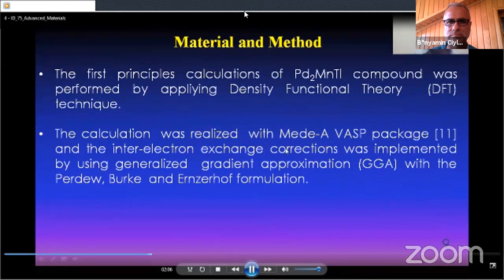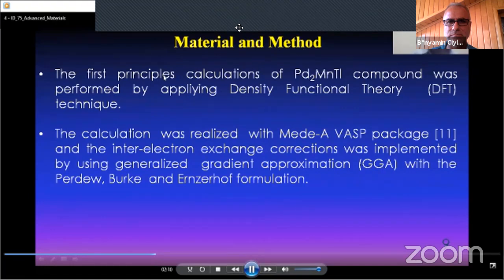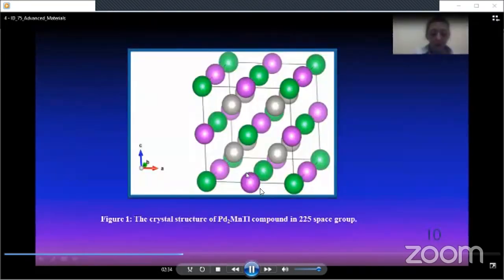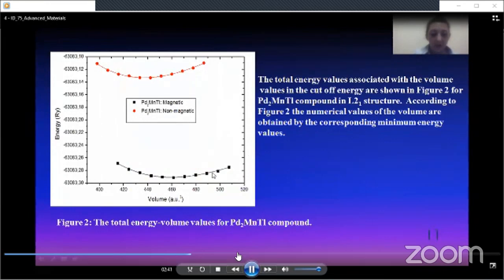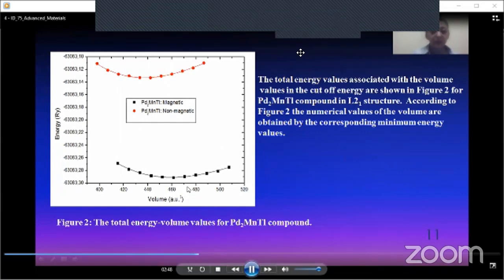In this part, I will talk about materials and methods. The first principles calculation of the palladium manganese thallium compound was performed by applying density functional theory. This calculation was realized with the program, and the electron exchange correlations were implemented by using the generalized gradient approximation. Figure 1 shows the schematic representation of the compounds. The total energy associated with the volume values and the cutoff energy are shown in Figure 2. In Figure 2, numerical values of the volume are obtained by corresponding minimum energy values.